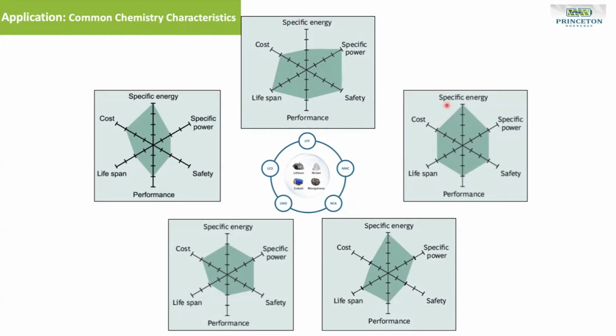So that's why when I was in the research group, we had a lot of research grants focusing on how to improve the NCM materials with much more safety, to control the combustion flame or make it safer. However, this is still the major challenge for these materials. A little bit more information on NCM: the ratio can be 1:1:1 for nickel, cobalt, manganese, but you can also have a high nickel content like NCM 6:2:2. That means the ratio is 6, 2, and 2. In the past, we tried to increase the nickel content as much as we can, because higher nickel content shows higher energy density. However, it gives you more risk with safety.